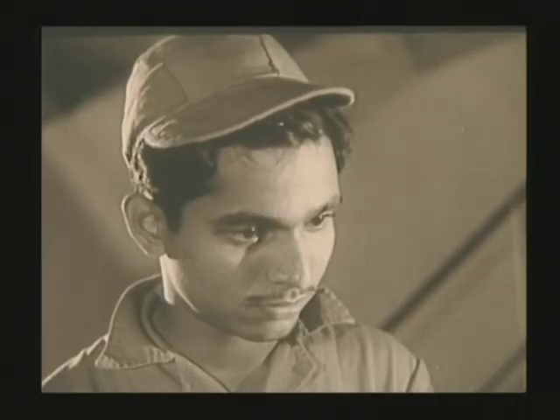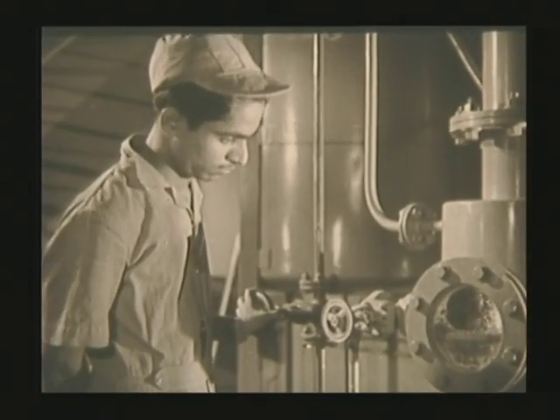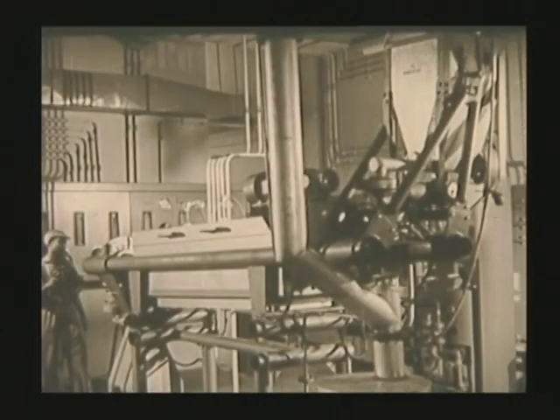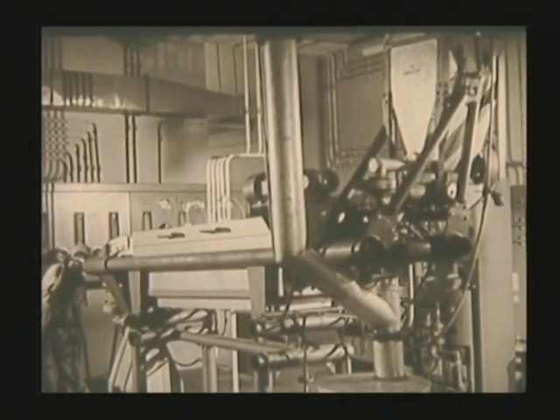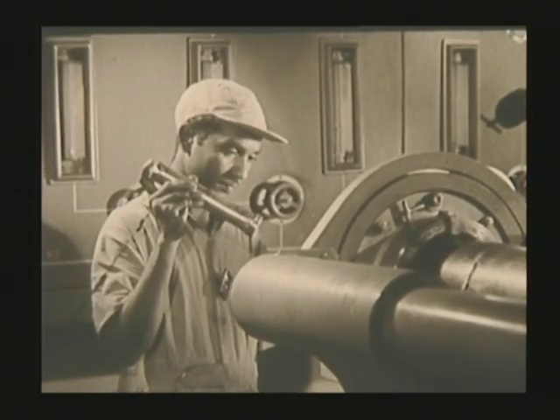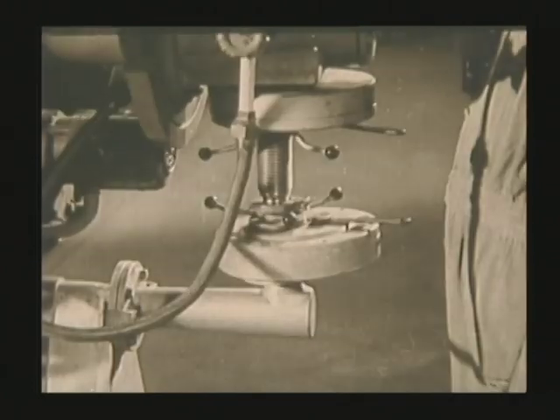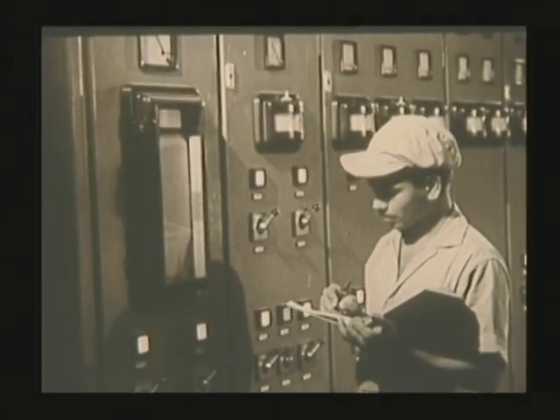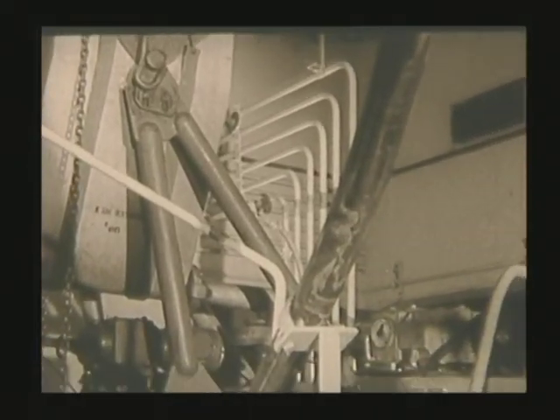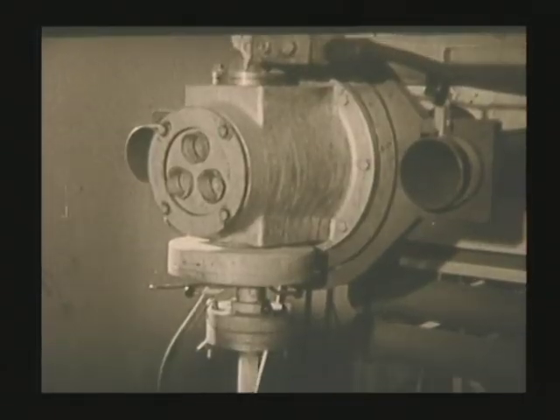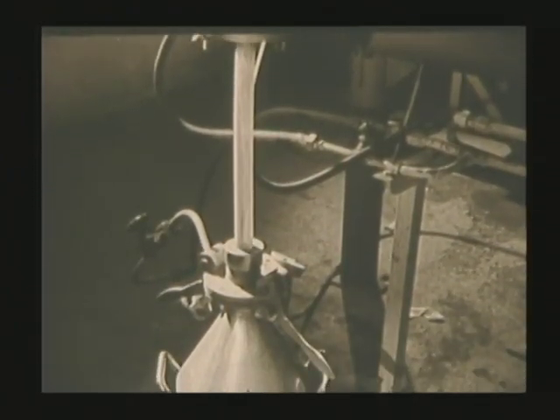The solvent used is tributyl phosphate and kerosene. The resulting nuclear pure uranyl nitrate is then treated with ammonia to obtain ammonium diuranate. This is calcined at 450 degrees centigrade to give uranium trioxide. The trioxide is reduced to dioxide by treatment with hydrogen at about 600 degrees centigrade. Treatment with gaseous anhydrous hydrofluoric acid converts the dioxide into uranium tetrafluoride, which is the most suitable material for reduction to metal.